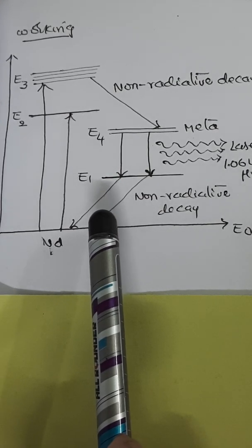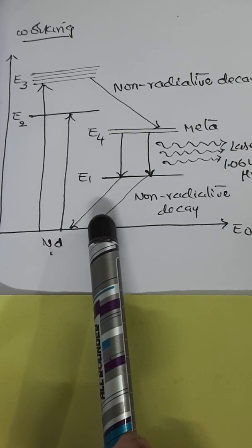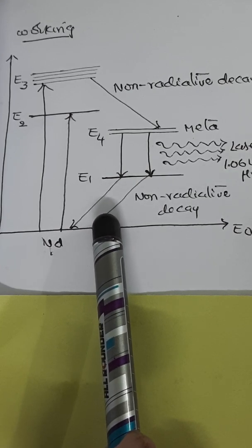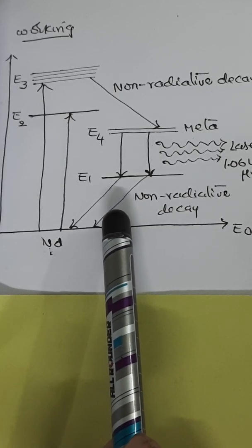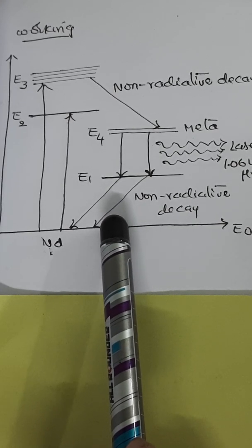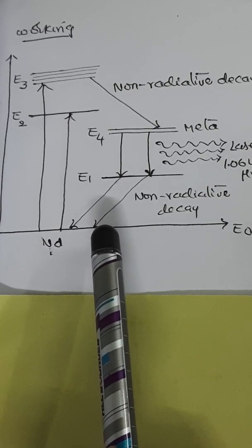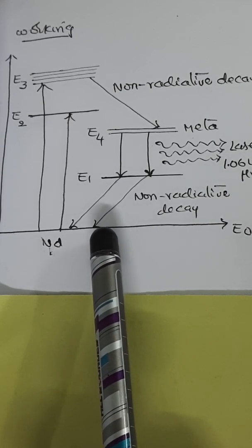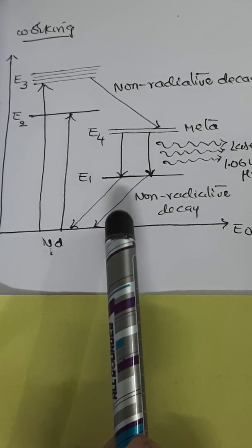It can be operated at power levels of up to kilowatts. It can be directly Q switched with chromium 4 plus YAG. Its lasing wavelength is almost 1064 nanometers, and its best absorption band for pumping is 1 nanometer wide and located at 807.5 nanometers. But the only disadvantage in this is that its electronic energy level structure is very complicated.